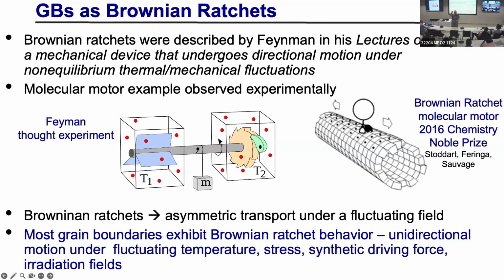Imagine you look at the stress-strain curve in a single crystal, and I repeat it where I superimpose on top of the stress this little oscillation. It should be different. It's a macroscopic experiment. If you're looking in a TEM, you should be able to see it as well. So I think it's actually quite generic, and it really only has to do with the symmetry or asymmetry in the structure, and the consequential symmetry or asymmetry in the migration barrier profile. And once you have that, all this other stuff just follows.